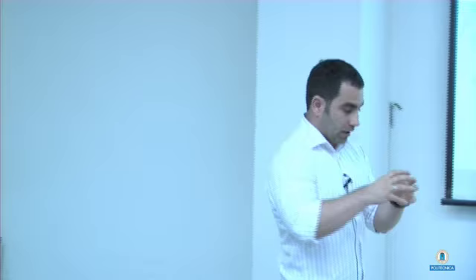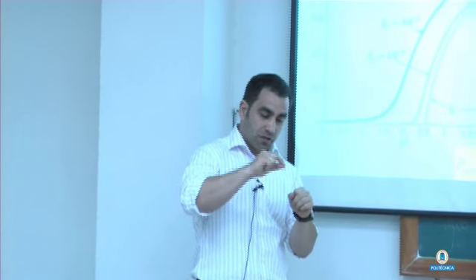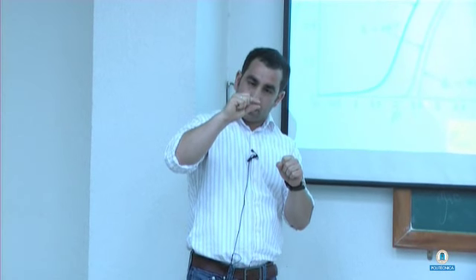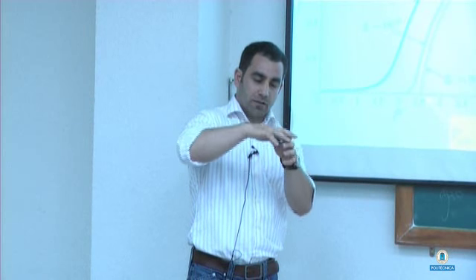And this correlates certainly well with the experiments of Gent and Lindley. In their experiments, they were trying to have a huge hydrostatic pressure in the center of the specimen, right? And if you make the disk very thin, then you can compute what is the pressure in that center of the specimen and see if it correlates with 2.5 mu, the mu of the rubber. And the experiments correlate certainly well. Okay,